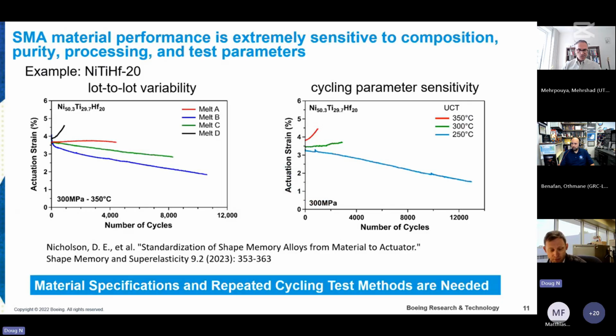So those are the ones that are published. We're not done yet. We're still working. Shape memory alloy material performance is extremely sensitive to composition, purity, processing, and test parameters. I'm using nickel titanium hafnium 20 here as an example. We can see in the plot on the left, these are fatigue cycling tests. I have here 4 different melts. We targeted the same nominal composition: nickel 50.3, titanium 29.7, hafnium 20, and just very small differences in nickel content and material cleanliness will produce very different results. So you can see here 4 different melts having a very different response.